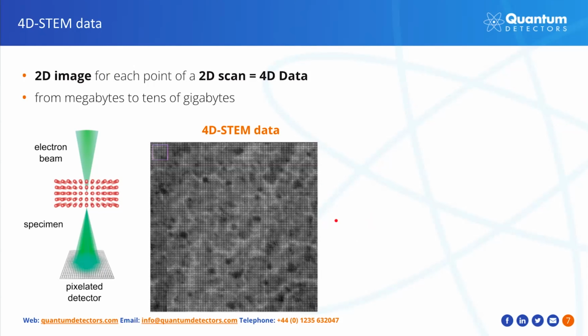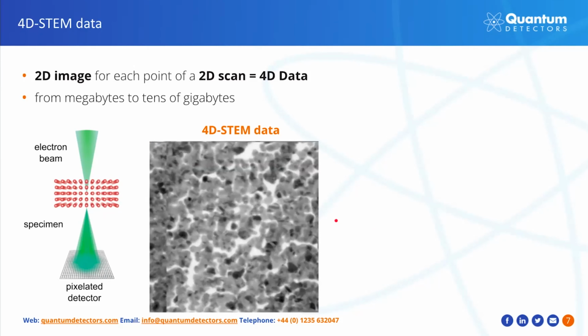The image is, however, affected by the pixelation, but once we remove the dark areas from around the disks, which we started with when we zoomed out, we can clean up the image. This is now approximately corresponding to the bright field image of the sample, which was a gold polycrystalline film in this case. Collecting the full information about the transmitted beam gives researchers additional advantages.